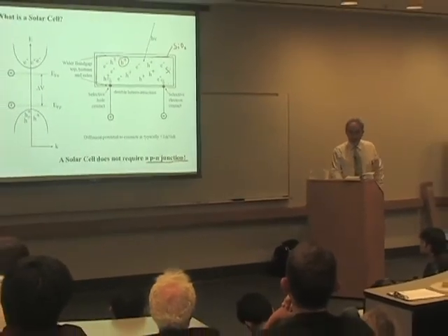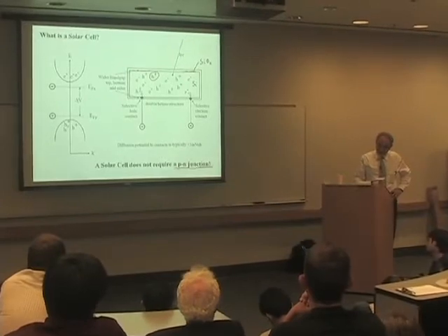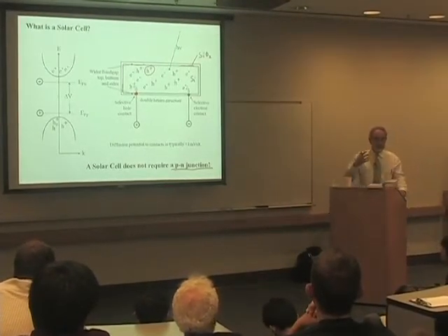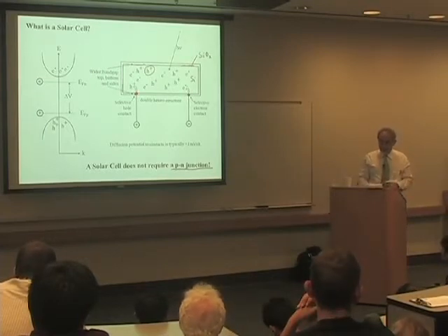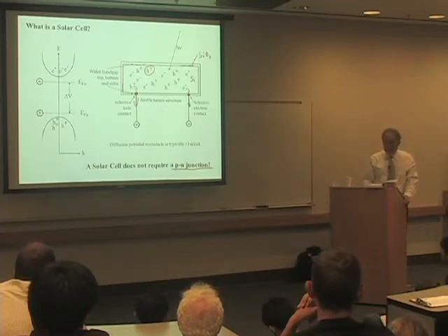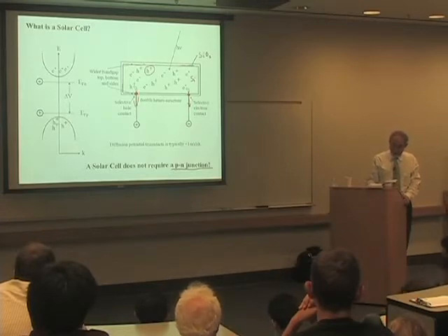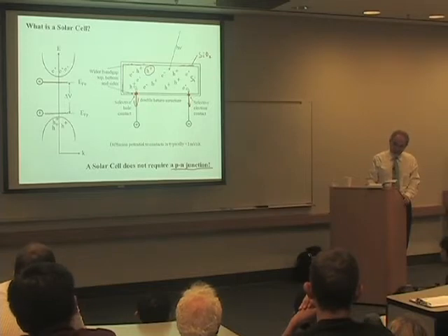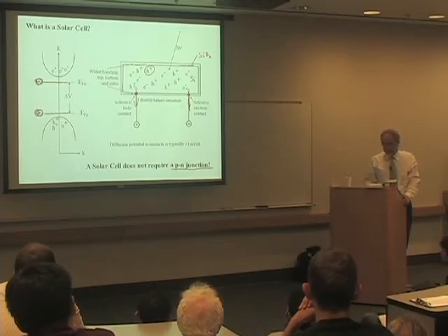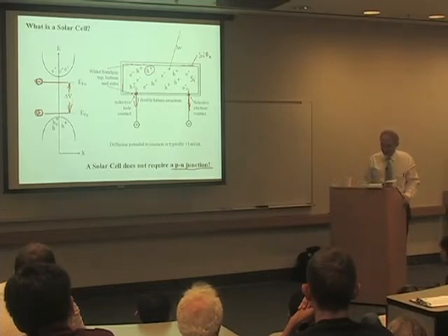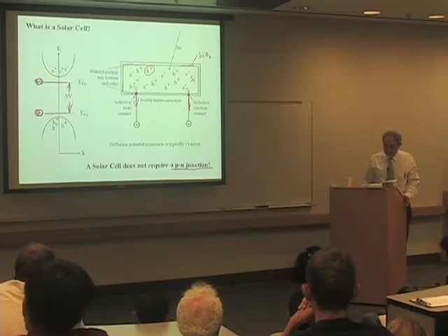Let's go on. Now you've built up the high density of electrons and holes. Now you need one more thing. You need a selective electrical contact. And luckily, in metallurgy, there are ways of making contacts that only allow holes to pass. So you make a p-type contact there, an n-type contact there. And this tremendous density of electrons and holes that you built up in this bucket, now the electrons go out through their contact, the holes go out through their contact, and they each go out at a separate voltage. Why? Well, the great thing about semiconductors, you can have not just one Fermi level, but two Fermi levels, a separate Fermi level for electrons and holes, and that represents essentially the voltage of the electrons. So this wire is essentially connected right here, and the other wire is connected to the other quasi-Fermi level. And the difference between these is the output voltage that you get. And you'll see later that the voltage goes as kT log of the carrier density. So that's how a solar cell works.